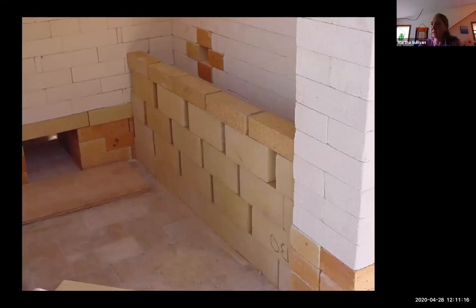And looking inside of the kiln, there's something called a bag wall. As the flames come into the kiln, they hit that bag wall, which is made of hard brick. Some of the heat filters through, as you can see through the holes, but most of the heat goes up to the top of the chimney. And it's called a sprung arch downdraft kiln because the heat rises up to the sprung arch and then down back to the chimney and out the back of the kiln. So there's full circulation from bottom to top and back to bottom again to try and get the kiln to be even.